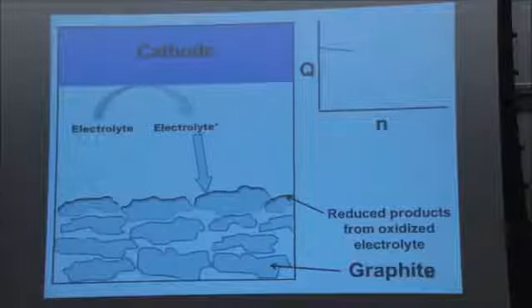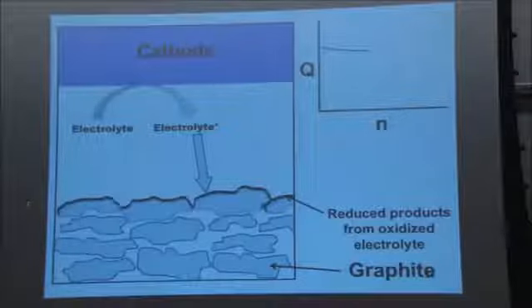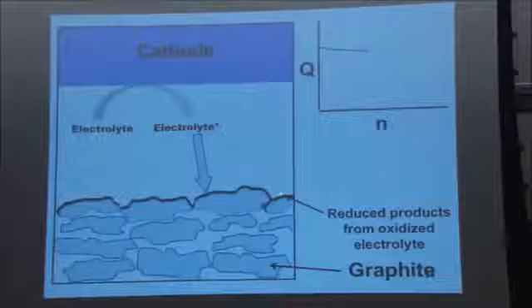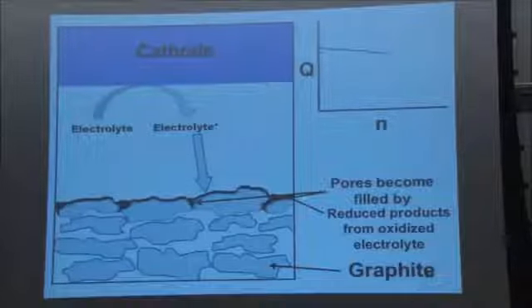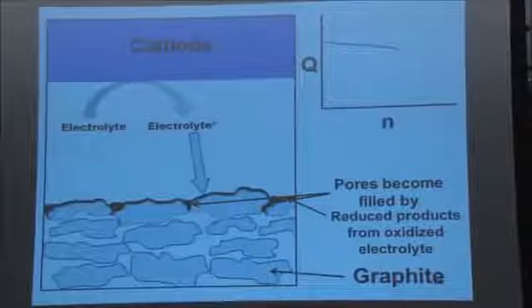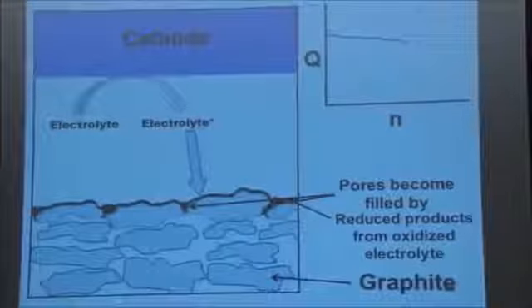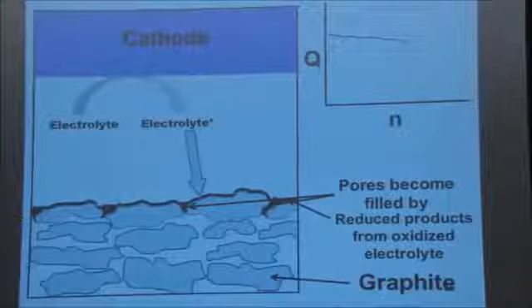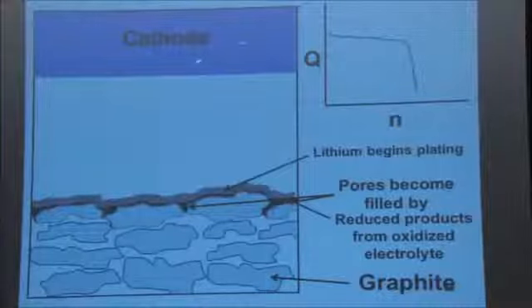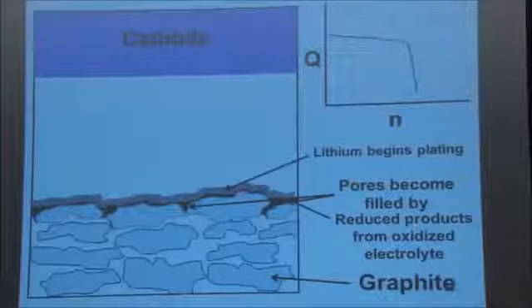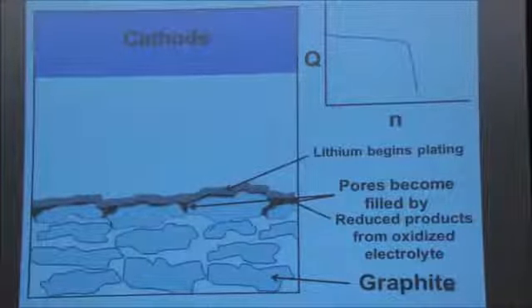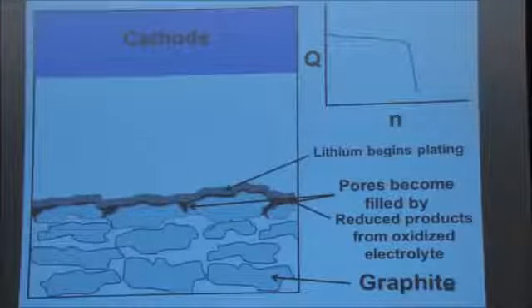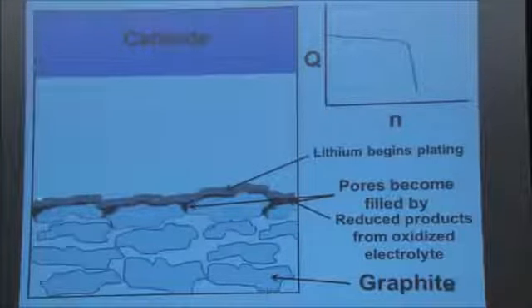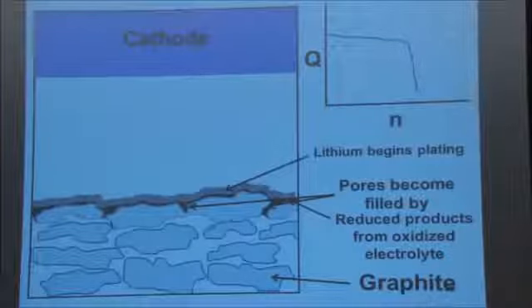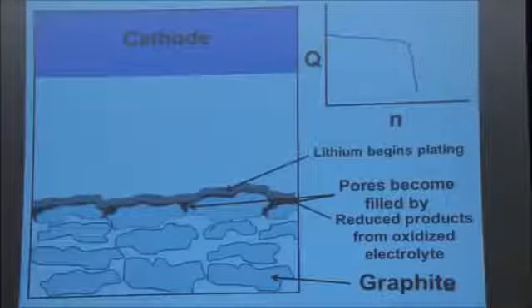And you cycle some more, and the layer of junk gets thicker, and the pore openings start to get closed off. And you cycle some more, and the pores ultimately become filled. And now it's very hard for the lithium ions to penetrate into the back of the electrode because it's blocked. And then lithium plating begins on the surface, and the capacity dies. Okay, so that's what we believe happens. And when you take these cells apart at the end of life, you see a lot of evidence for lithium plating in certain parts of the electrode.